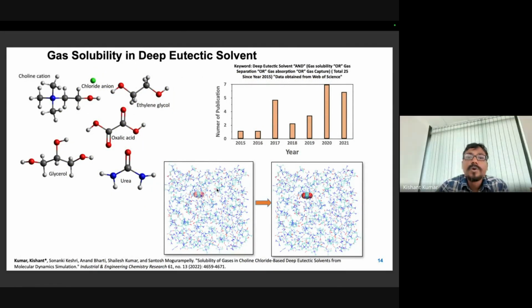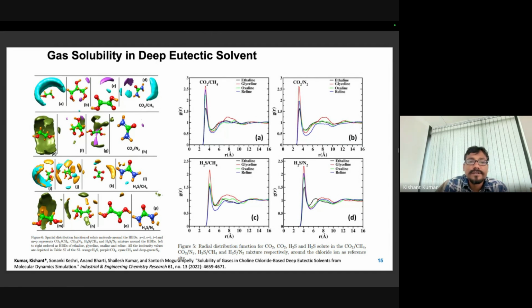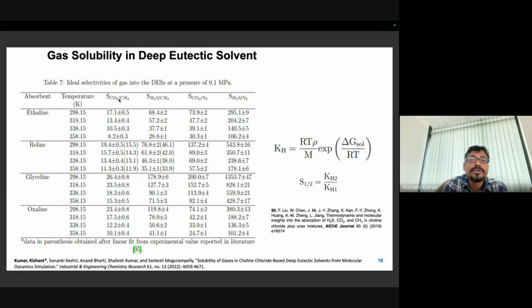Yes. So another application is gas solubility in solvents. Here I have taken some green solvents. In industry, people use solvents to separate CO2 from a CO2 N2 mixture. So here I tried to take some green solvents and calculate the solubility. You can see the selectivity of CO2 with this solvent we got is 19.4, and your experimental value is 15.5. So you can see how close we got to the match, 11.3, 11.9 from the experiment.